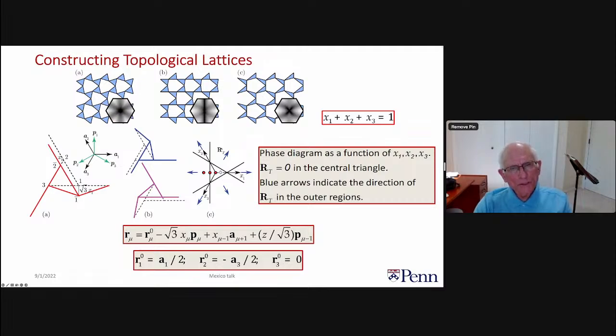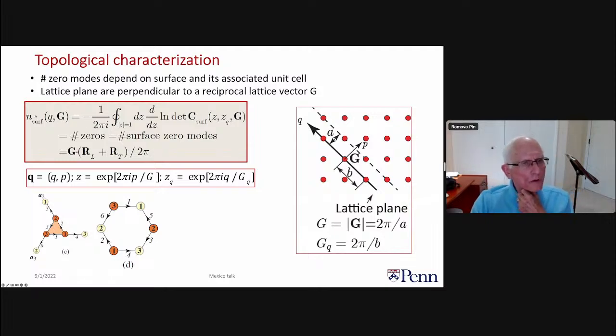This lattice has a polarization RT, which I'll discuss in a moment, but basically in each of these three different directions, the blue arrow is telling you the direction of a polarization vector, which is analogous to what you see in the Su-Schrieffer-Heeger model, and it points typically from here to here. So here's where we come in. The number of surface modes on a surface characterized by a reciprocal lattice vector G. You recall the reciprocal lattice vector G, when it's perpendicular to a lattice plane, points perpendicular to the line of the lattice plane and has a length scale between neighboring straight lines of bonds, which is given by this formula here, where B is the length along this direction.